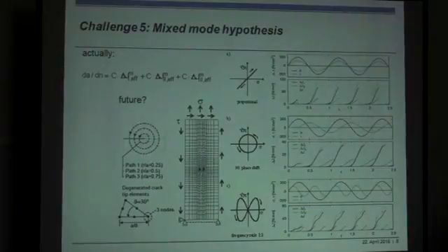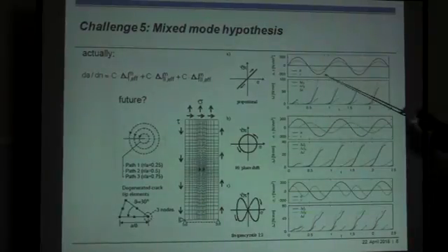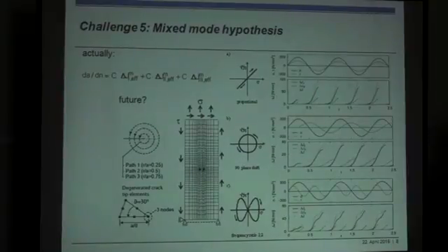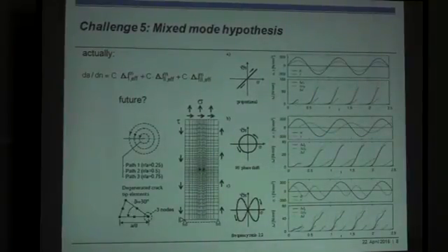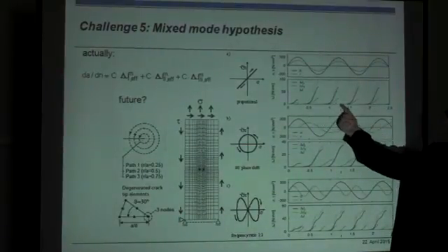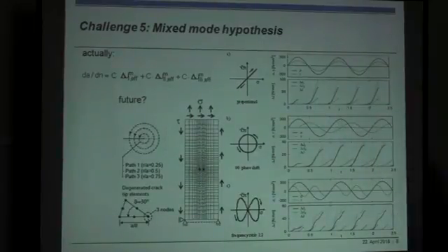increase and increase. If we would continue to calculate J integrals after this reversal point, then the result of the J integral would go down. So you will reach a maximum in J integrals, and this is the indication to stop that integration now. So this is a half cycle here. The next half cycle gives you the same answer. It goes from here to there, then from here to there, and so on.